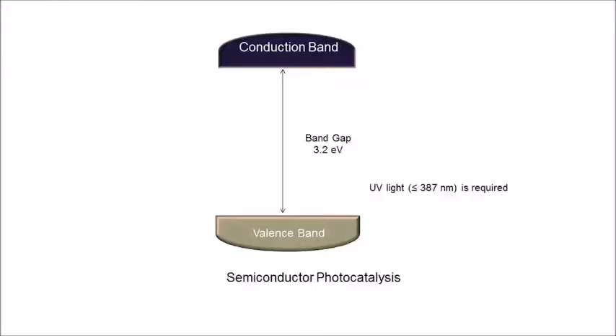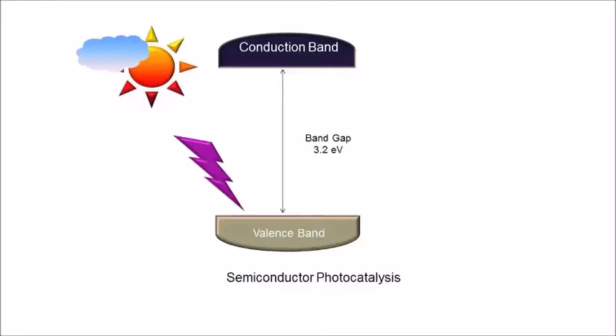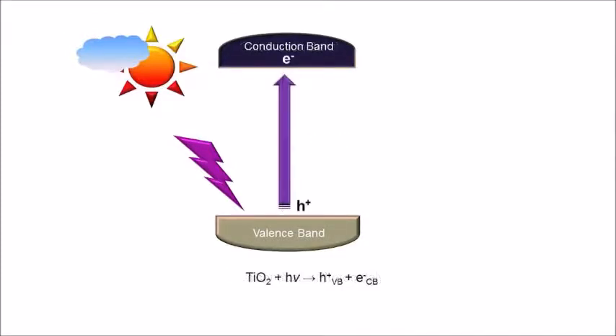When light energy greater than the band gap energy hits semiconductors such as titanium dioxide, electron from the valence band will be moved to the conduction band. In the case of anatase form of titanium dioxide, the band gap is 3.2 electron volt. Therefore, UV light or ultraviolet light is required to initiate the photocatalytic reaction. The absorption of a photon from the ultraviolet light excites an electron to the conduction band, which generates a positive hole in the valence band.